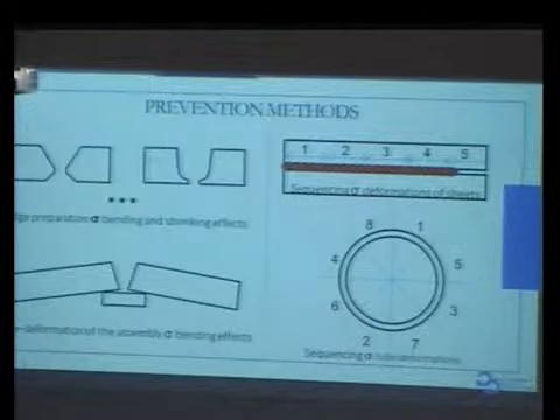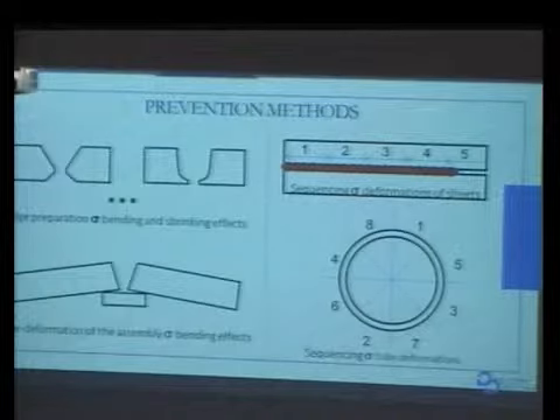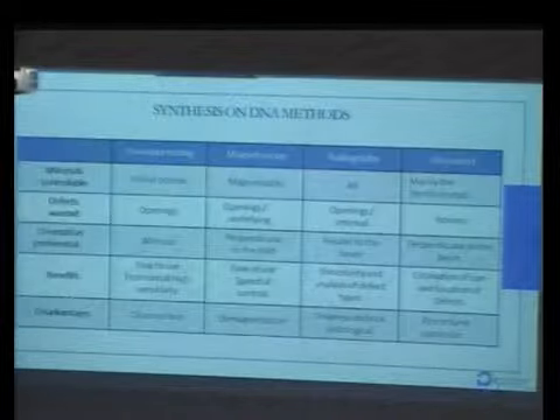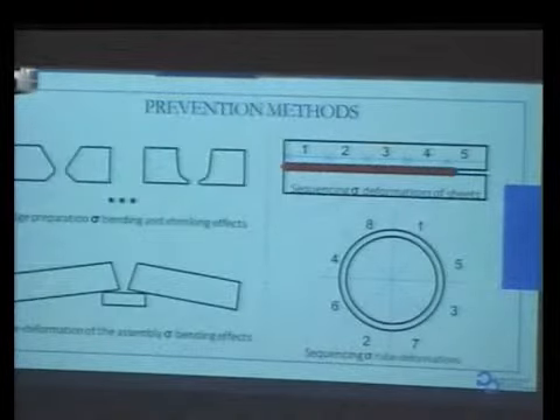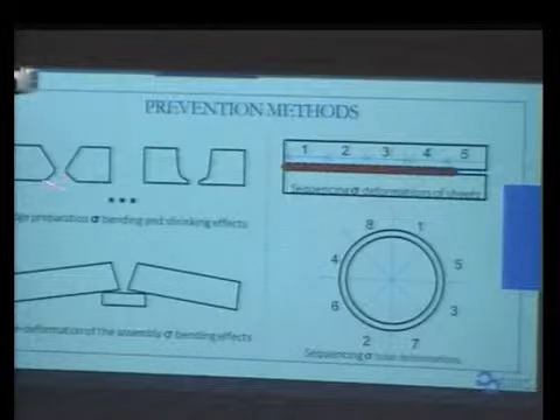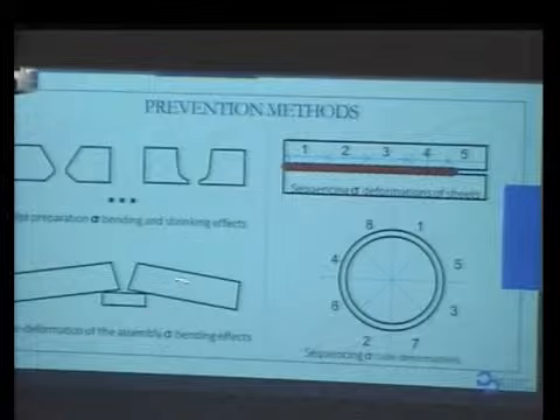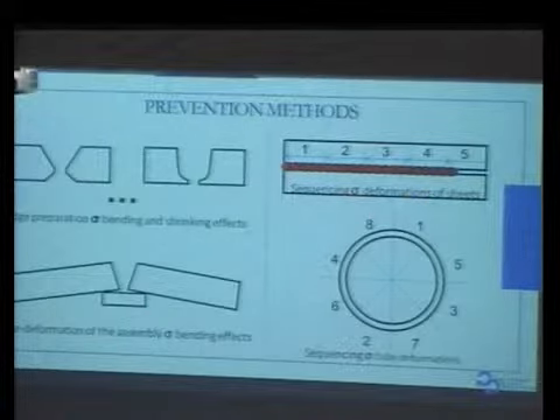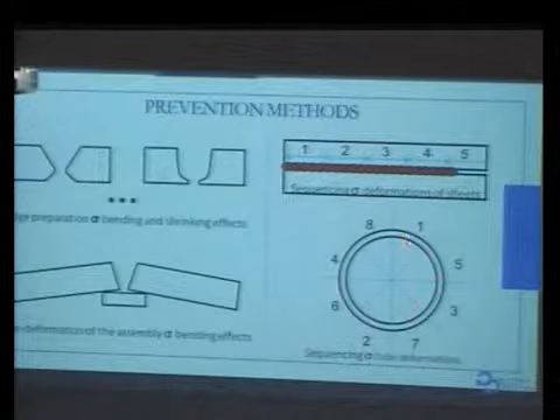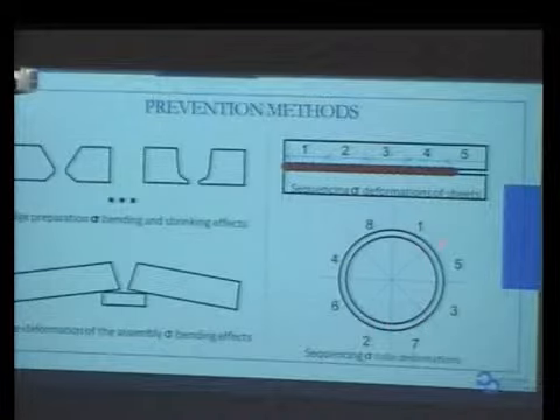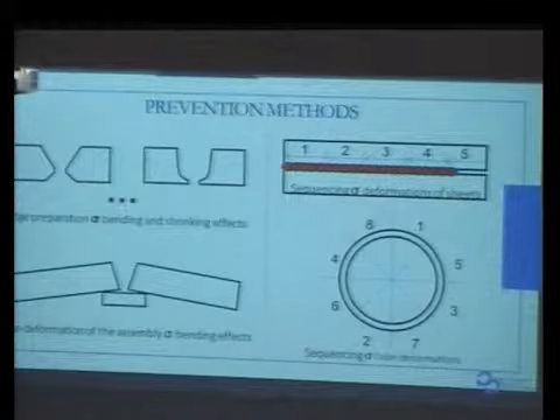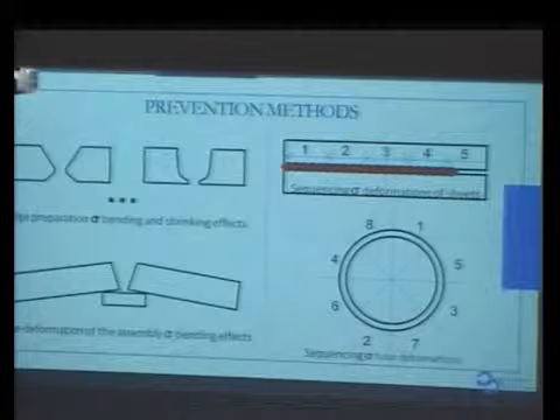And you have to prevent it with different methods: edge preparation, or pre-deformation before welding, and sequences for welding. When you weld a tube, for example, you don't weld continuously, but you make 1, 2, 3, 4, and so on. You have to prevent it. When you have to weld, you have to think about the consequences of welding.